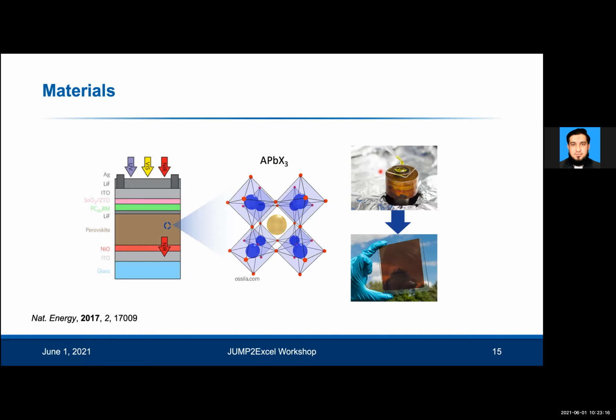The advantage of this material is that it can be made by solution processing, processed at very low temperatures of up to 100 degrees Celsius. Now contrast that to silicon, which needs to be processed at above 1400 degrees Celsius. And you can see that the carbon footprint of this technology will be quite low. And in fact, if you look at the energy payback time, which is the time in which you need to have a solar cell outdoors to harvest energy before it recovers the energy it took to make that technology, for crystalline silicon the energy payback time is a few years, whereas for the perovskites, it's only a couple of months. Simply because this technology is now very efficient, but the energy required to process this material is quite low because it requires relatively low processing temperatures.